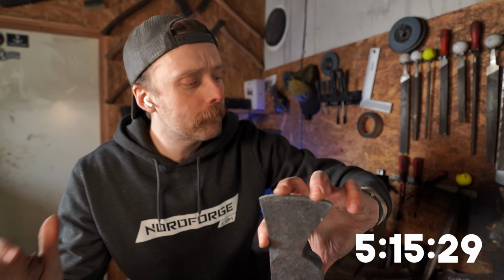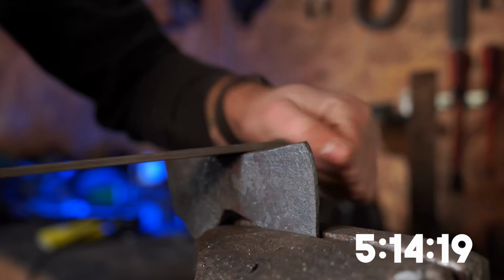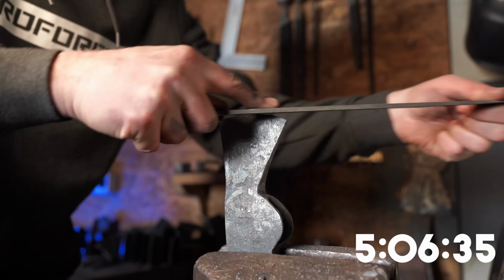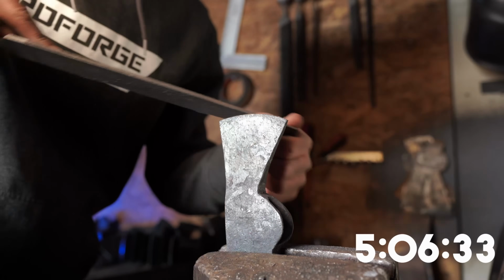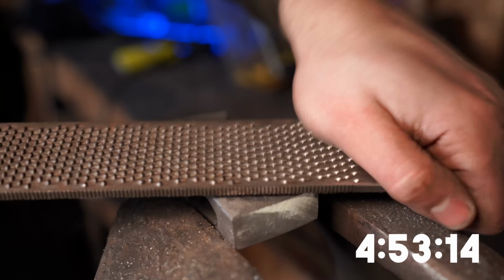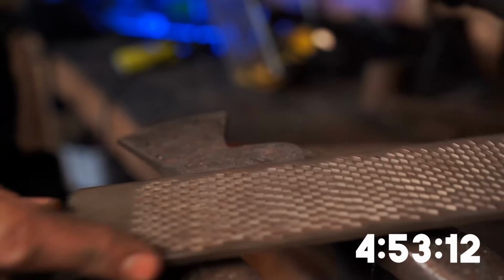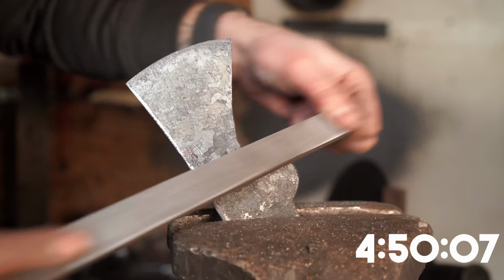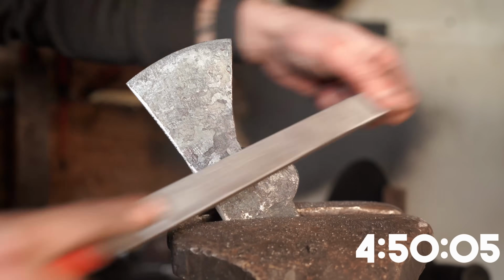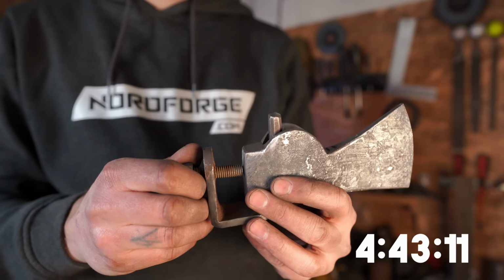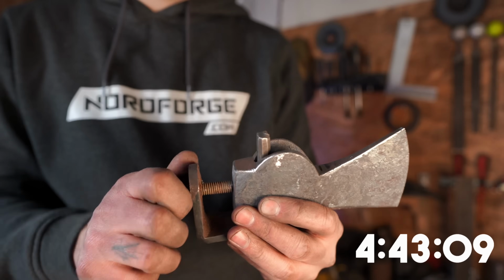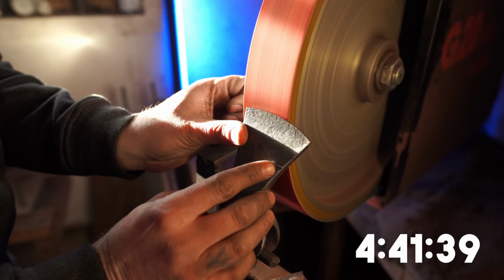Alright, so it's been about 40 minutes now, and the axe is now cool enough for me to hold it without burning myself, which is very good because now it's time to clean it up and get it ready for heat treatment. And here, almost immediately, I get to enjoy the fact that I took the extra time during forging, because now I barely have to grind anything. Just a quick touch up with the file and we're off to grind the edge, which is very nice if you don't like grinding, like me.